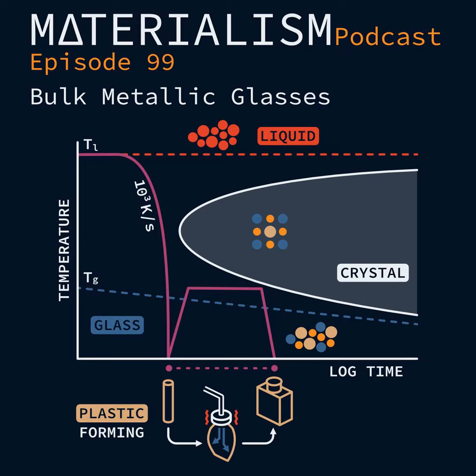Is it removed like a flux, or is it actually incorporated into the final structure as a secondary phase? So the yttrium is not removed. The yttrium oxide just floats on the surface, so it can be subsequently removed in a casting process. You take it out. There's also fluxes, right? The most common one is boron oxide. In fact, this is when we developed these ridiculous, where I said you can keep it 100 seconds at 1 degree. So the cooling rates are incredibly slow, right?